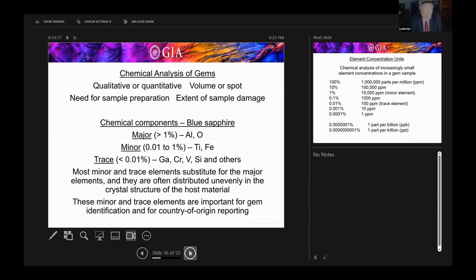Now, I just use blue sapphire as an example here. In a gemstone, there are major, minor, and trace elements. In this case, the major elements are aluminum and oxygen. Minor elements from about 0.01 to 1%, in this case, titanium and iron, and below about 0.01% roughly, gallium, chromium, vanadium, silicon, others. These minor and trace elements substitute for the major elements in the crystal structure, but they're oftentimes unevenly distributed in the material. This is important because if you're doing a spot analysis, it's rather difficult to make sure you're analyzing the right location to make the chemical analysis. And again, this minor and trace element chemistry is very important for gem identification and for country of origin reporting.